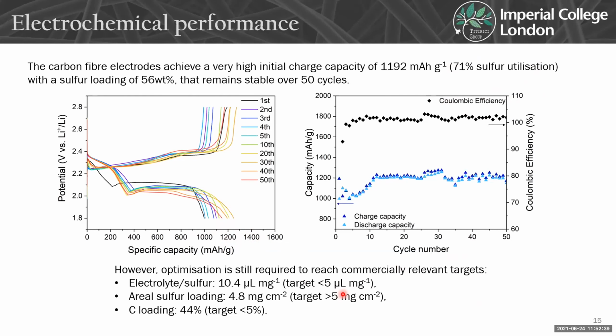So the commercially relevant targets, typically we're aiming for a much lower electrolyte to sulfur ratio. At the moment I'm using 10.4, but the target really is less than 5 microliters per milligram. And as I said before, we want to increase the sulfur loading. So here I've loaded it with about 56 weight% to match the pore volume, and that is equivalent to an areal sulfur loading of 4.8 milligrams per centimeter squared, but the target is to reach over 5. And then again here my carbon to sulfur loading is quite high, and the aim is to reduce it to below 5%, but that is quite an extreme target. So there's still some work to be done there.